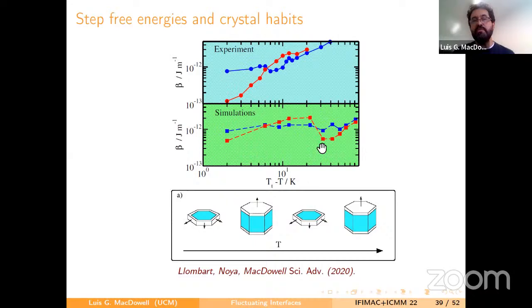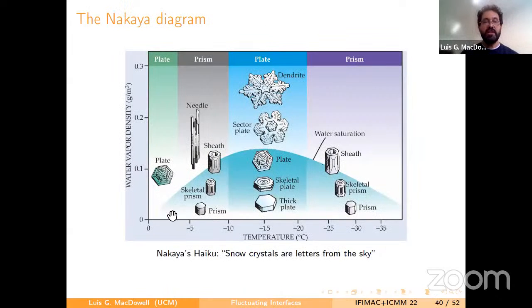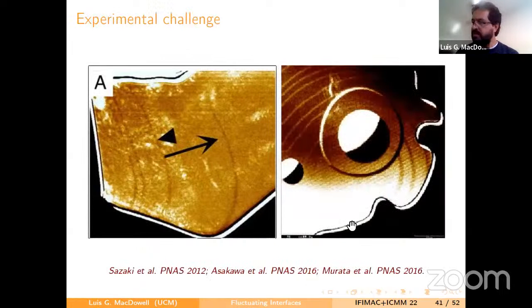So by our computer simulations, we can explain at least 3 of these regimes in the Nakaya diagram. They look just as expected from the Nakaya diagram. And that's why Nakaya wrote this beautiful haiku, which says, "Snow crystals are letters from the sky." Because just by exploring the shape of the snow crystals, you can tell at what temperature and what humidity they grew 10,000 feet above Earth.